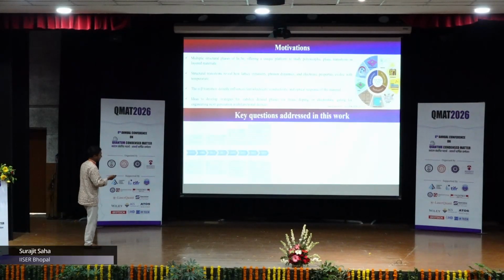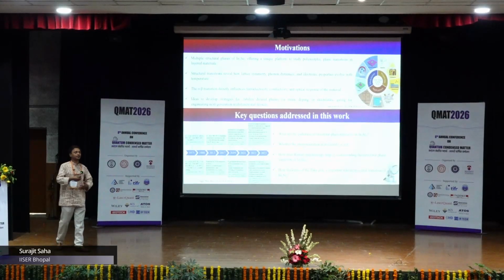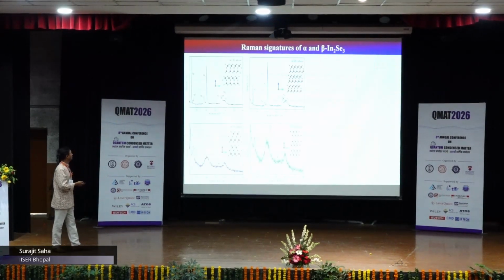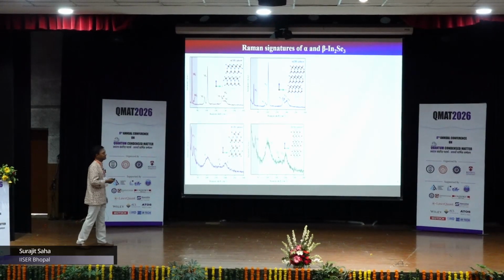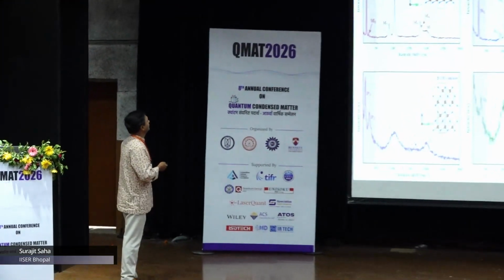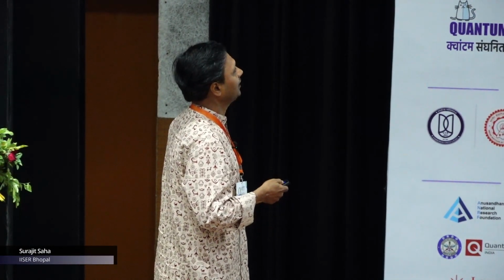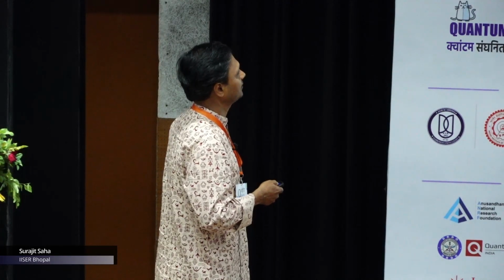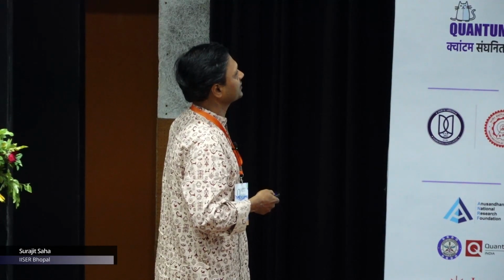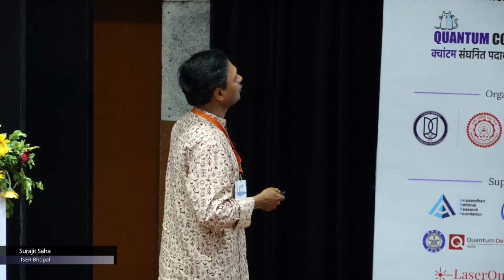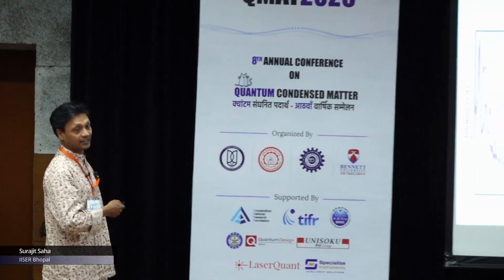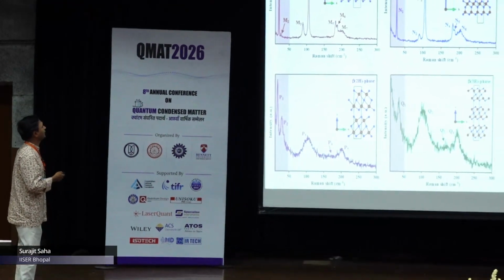All right, so we have certain questions to start with. We basically wanted to look at the various polymorphs of indium selenide and how it evolves from one structure to another. And that's what we started with in the experiment. Now, in terms of Raman signatures, if we grossly want to see, this is the alpha 2H structure and the corresponding Raman signature. And this is the alpha 3R structure, the 3-layer stacking, and this is the 2-layer stacking. If you notice, the high frequency modes are almost the same, except the low frequency band, which is shaded here. So you have only one component here, and we have 2 components here. So this is the distinction of the 2 structures for 2H and 3R.